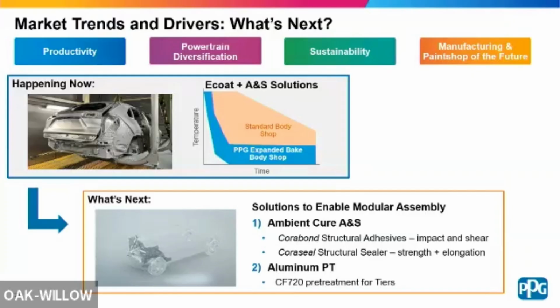Yeah, I'll just add, and I think Paul alluded to this too, one thing that we are seeing for current customers a lot of times is they're not actually dropping the temperature. They're just increasing their line speeds. And the lower, broader bake window helps prevent cold spots, for example, of the adhesive. So you get full cure at the low temperature, or make sure if you have a heavier metal segment, you're still getting full cure of your adhesive or your Ecoat technology at the faster line speeds. And that is due to the complexity of other things that have to cure in that oven, like baffles and bake-hardened metals and things like that. So we're seeing innovation in those spaces as well, but that's why I think we're seeing higher throughput as being the initial push for this.